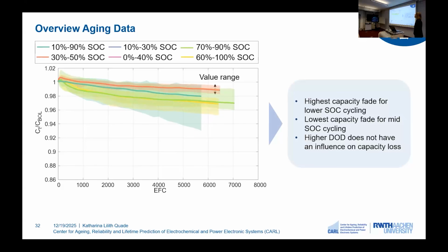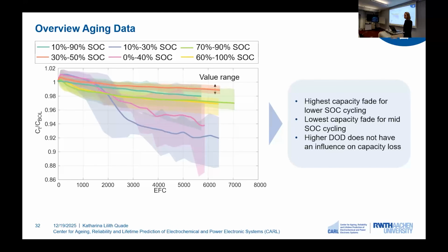And we can also include the conditions for the higher SOC cycling. And we can see again, very low capacity fade. And I can now include also the conditions for the low SOC cycling. And here we can see we have the highest capacity fade for these conditions. And we can also see that the higher depth of discharge does not have an influence on our capacity loss.